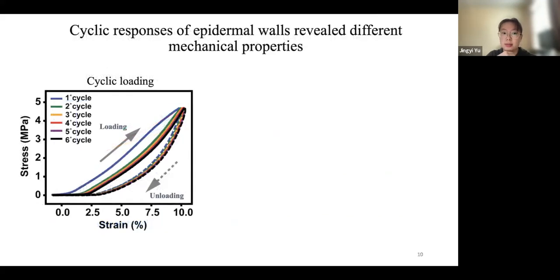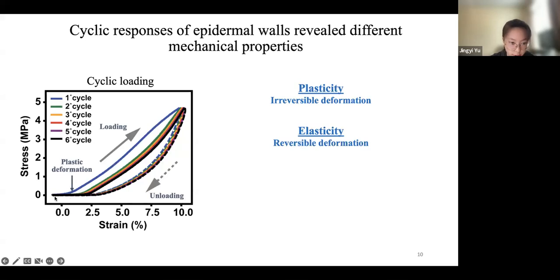Furthermore, we wanted to test the reversibility as well as the response of the cell wall when we load the material and unload it, and do it repetitively. How would the wall respond to that? We can see that after the first cycle, the second cycle looks different from the first, indicating that there is some irreversible deformation happening in the cell wall. The wall only starts to bear loads after this amount of irreversible deformation, which we call plastic deformation. Starting from the second cycle, going up to the sixth cycle, the curves basically overlap on top of each other, indicating that the cyclic loading behaves more like an elastic material, where the deformation remains mostly reversible.